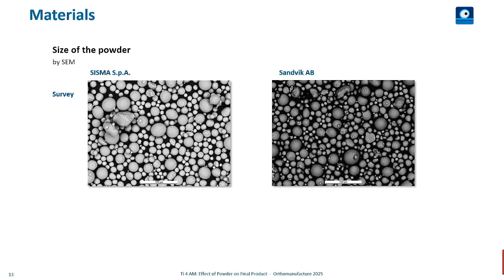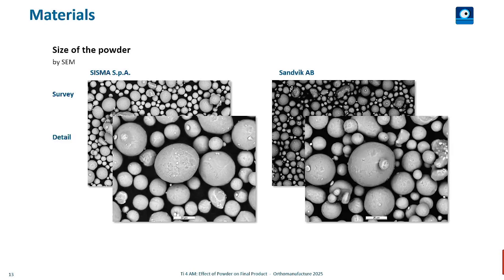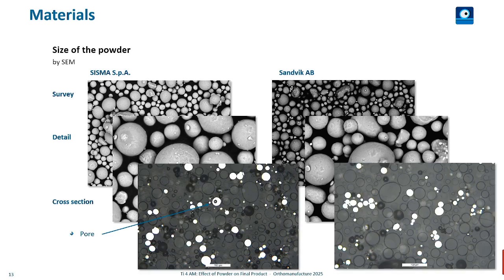If you look at the powder, we see quite some differences. We also see a relatively inhomogeneous distribution, so we have larger grains and smaller grains. Having a closer look, we still see very small powder particles, while we also have larger ones. And within a cross-section, you probably find even pores within powders. So if you want to have a pore-free material at the end and you start with a powder containing pores, it may be difficult.